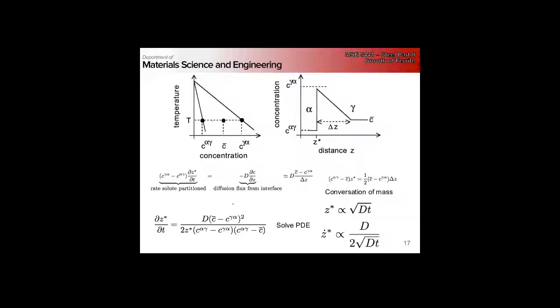So if we assume we're nucleating heterogeneously, but let's simplify the problem and think about it for a second. Just say we've got a JMAK scenario going on, nucleating at a constant rate. So then we nucleate, they start to grow, and as they grow, the growth rate slows down, but our nucleation rate is still sort of constant. So if these were to grow and fill up our space, what would it sort of look like?